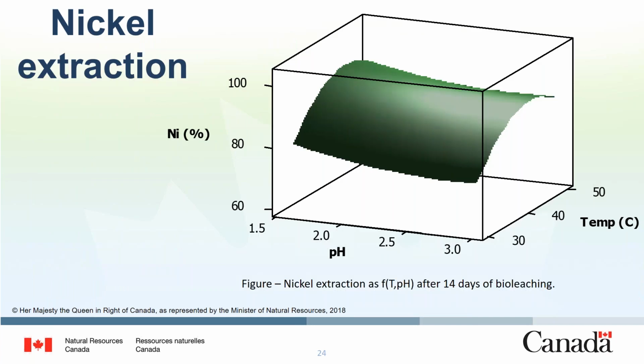Here we have a response surface of nickel extraction as a function of temperature and pH after 14 days of bioleaching. At both 40 and 50 degrees Celsius, nickel extraction plateaued after approximately 7 to 10 days, whereas nickel extraction plateaued after 14 days at 30 degrees. All bioleaching experiments resulted in 80 to 90% of the nickel being recovered in 14 days, suggesting a relatively robust process over the pH and temperature conditions examined in this study.